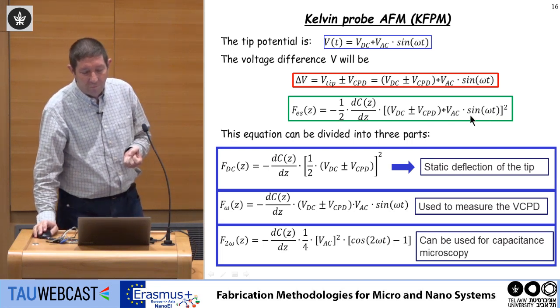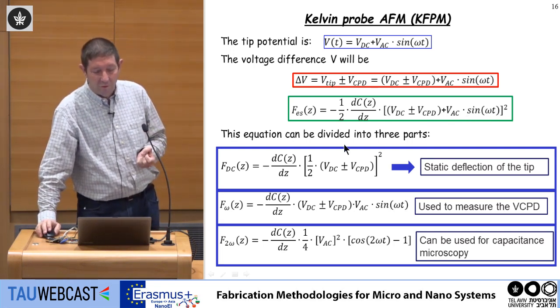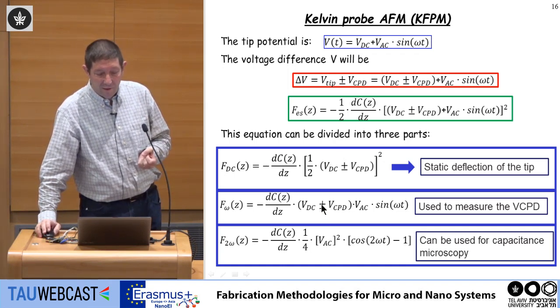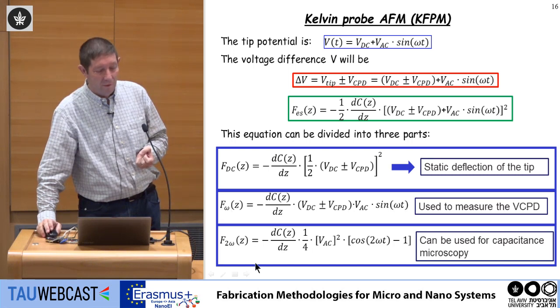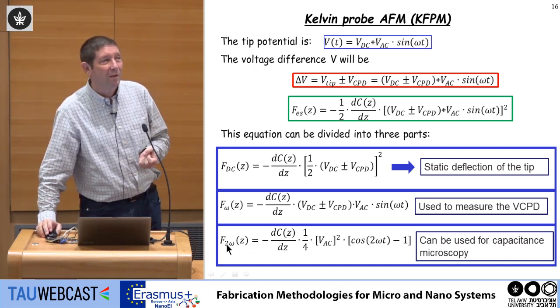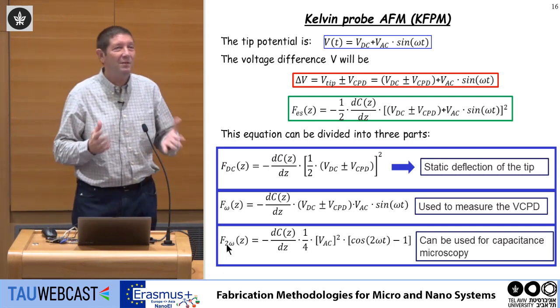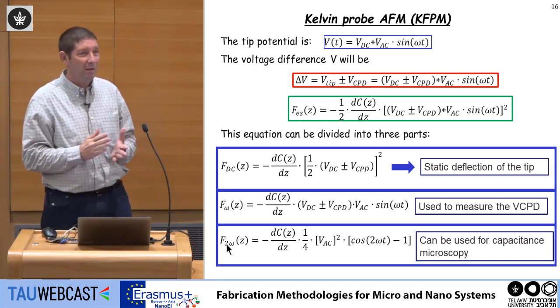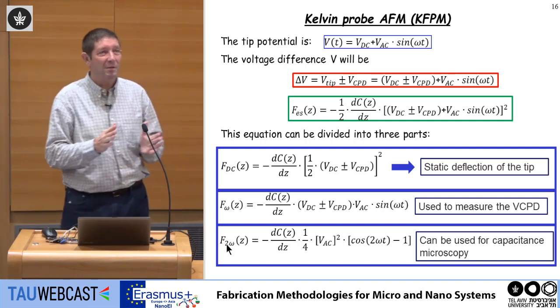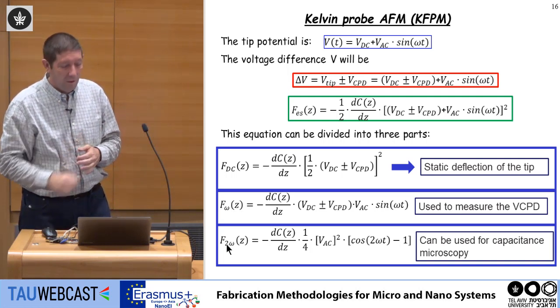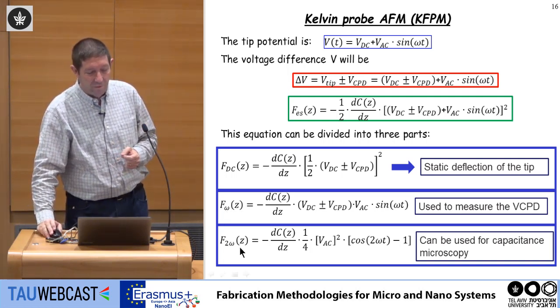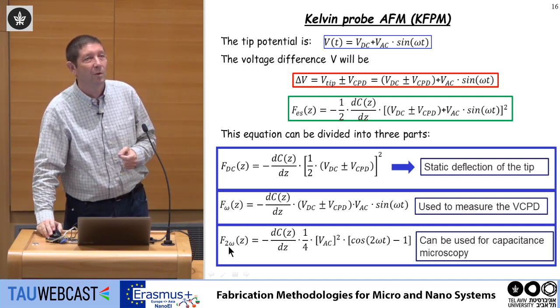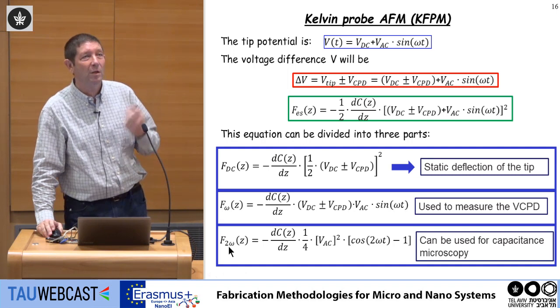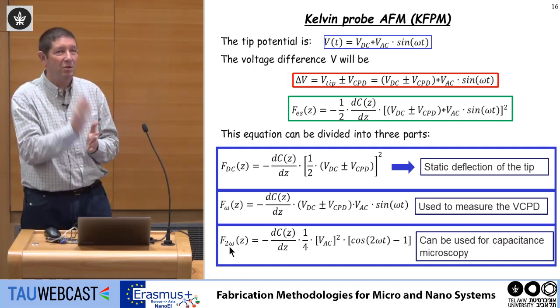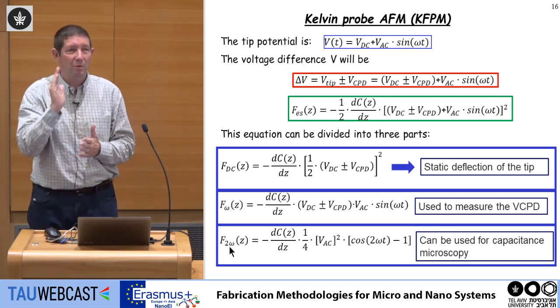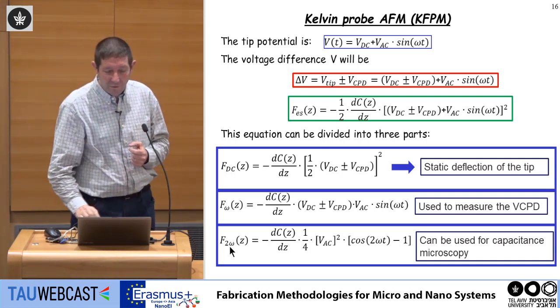If I look at this term, it actually contains three terms. One is a DC term. The second is a term that depends on the frequency omega. And the third depends on 2 omega. If you're an electrical engineer, it's very easy to measure the three of them separately. To measure the DC voltage, I take the signal and pass it through a low-pass filter. To measure the force at frequency omega or 2 omega, I use a phase-locked loop or a system called a lock-in amplifier, an amplifier I can use to measure the signal at frequency omega or 2 omega. So I can measure each one of the three components separately.